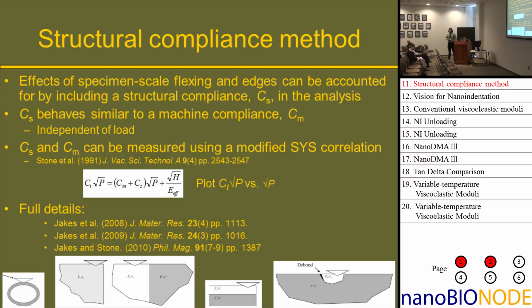This equation is easiest to use if your hardness and modulus are independent of depth. If they are, then a plot of the total compliance times square root of load versus square root of load will give you a straight line fit, and the slope would be the structural compliance. You can then correct your load-depth trace the same way you would for a machine compliance. With this method, you account for specimen scale flexing, free edges, interfaces, and also particles embedded inside of a matrix.